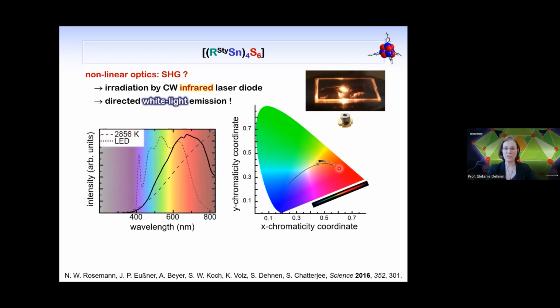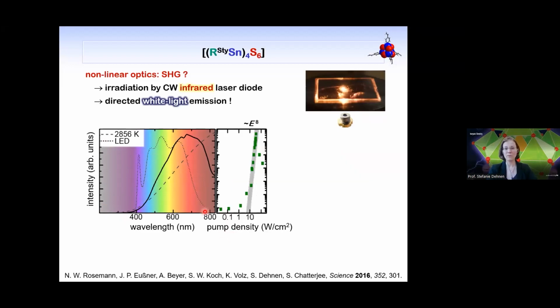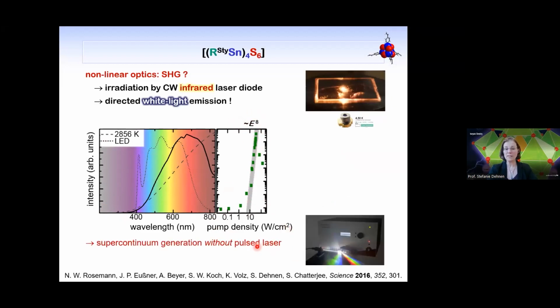And we approached this spot by increasing the power of the laser. So here at this point, we have this spectrum, which is very similar. And it's a broad spectrum, as you can see. Here you have the dotted line. This is the spectrum of a normal white light LED. It's a bit more into the blue, as known, and ours is a very warm white light emission. And we can see that it's a highly nonlinear process, so you have a scaling with the electric field to the power of 8. And this is the speciality. We didn't use a pulsed laser for it.